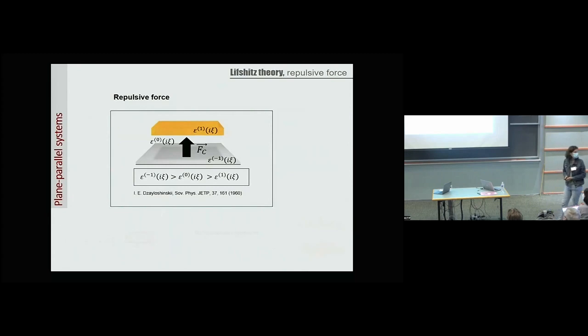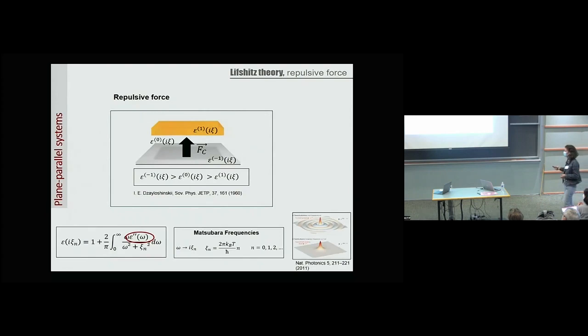Well, in the case of a plane-parallel geometry, it is well known that if you have dielectric functions satisfying epsilon(-1) > epsilon(0) > epsilon(1), it is possible that your force is going to be repulsive. But note also that this inequality is written in Matsubara frequencies. This means that we are rotating from the real axis to the complex plane, so that we are eliminating these rapid oscillations in our integrand, and everything is going to be much easier. When we do this rotation, we need to integrate the imaginary part of the dielectric permittivity over a wide spectral range. This is also a huge condition for us to make an experiment, because you don't always know the optical properties of your materials in such a large spectral range.